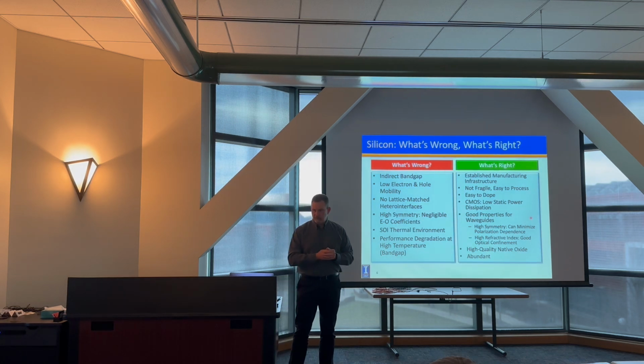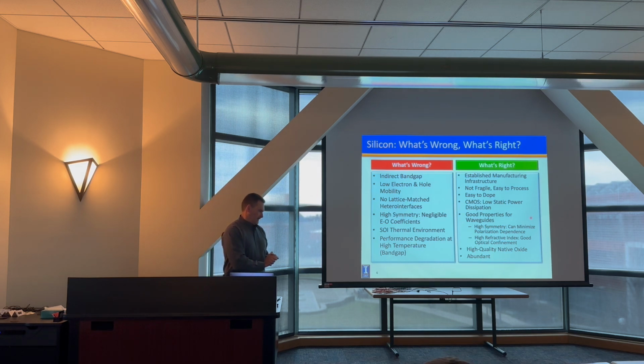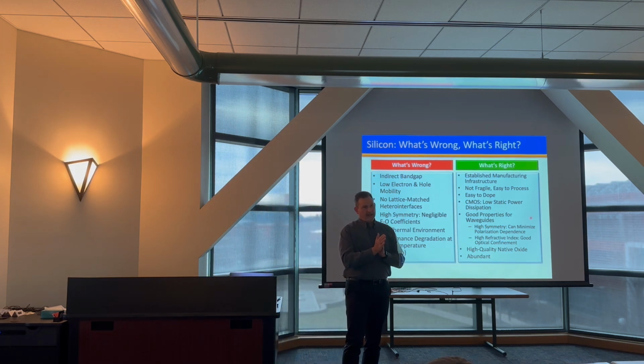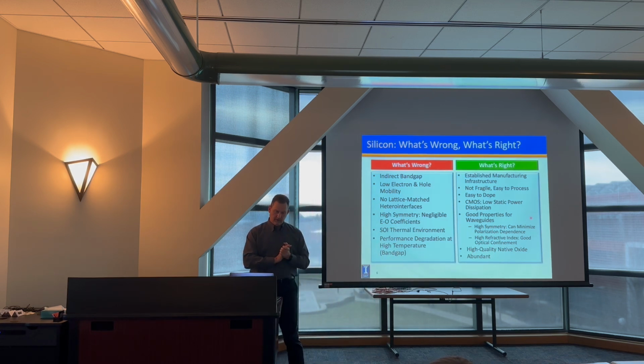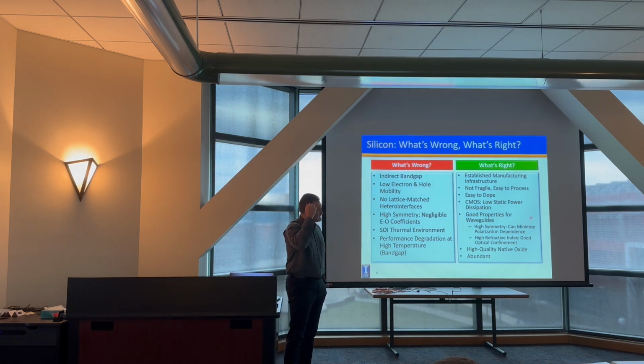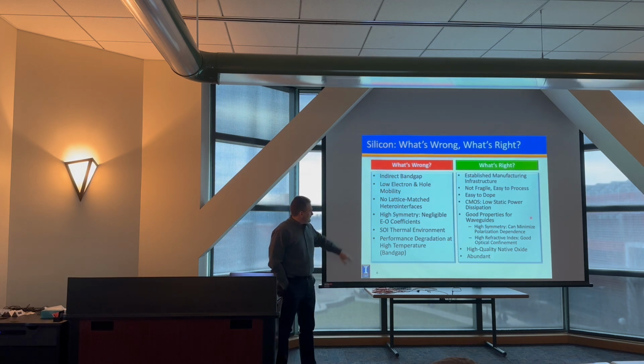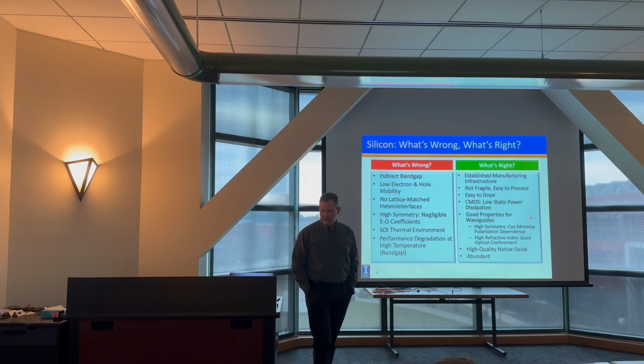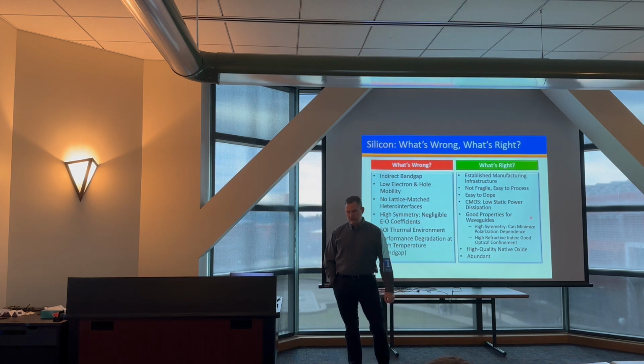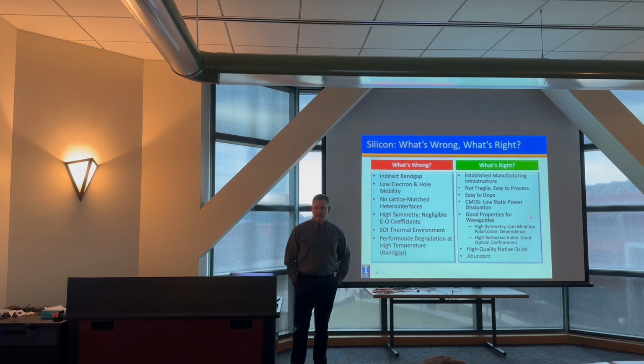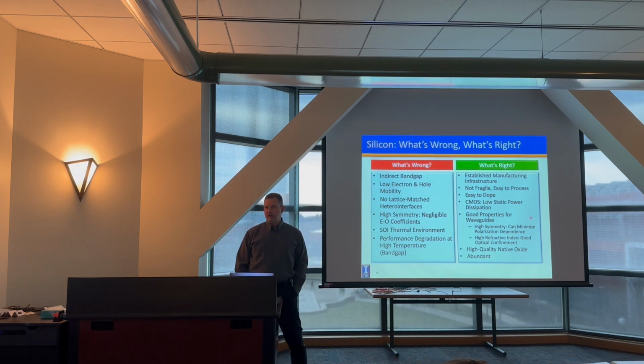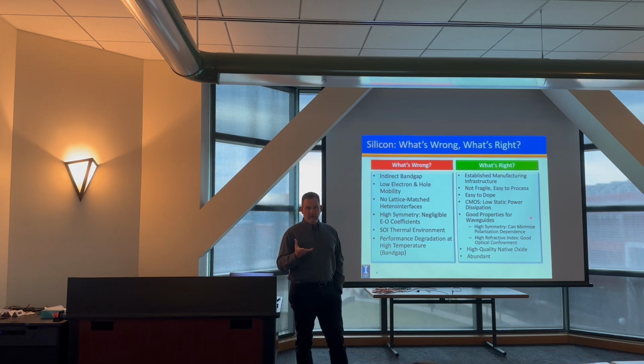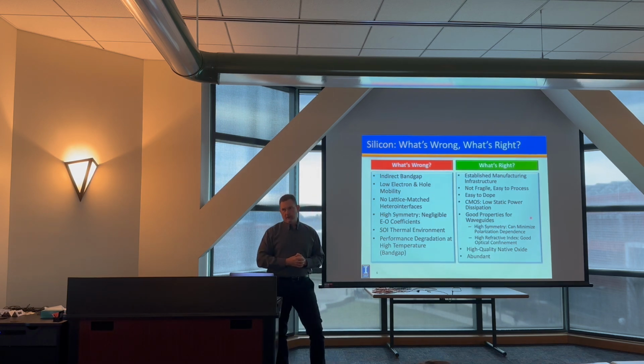So what's wrong with silicon? Well, first of all, it has an indirect band gap. For doing anything involving photons, indirect band gaps are undesirable because you've got the momentum problem. Compared to other materials, it's got a little bit lower electron and hole mobility, so it's slower. Silicon is silicon. You can't necessarily make complex lattice match other interfaces. The thing that makes it a good waveguide, that high symmetry, makes it a lousy electro-optic material. It has virtually no electro-optic effect, and the only way that we can make things like modulators is by creating a p-n junction and changing the carrier concentration in order to change refractive index.